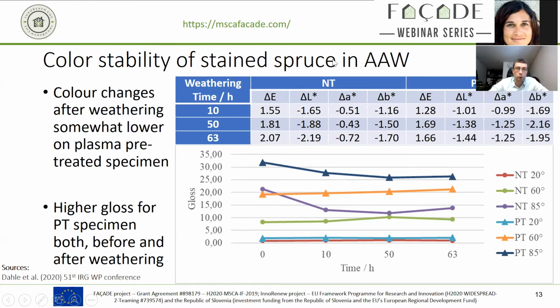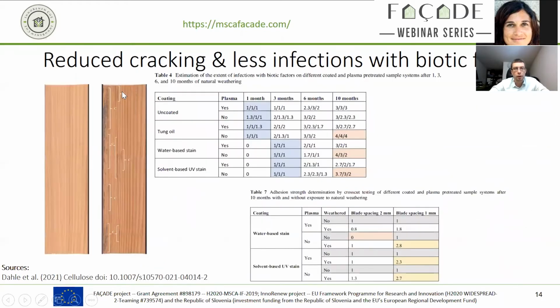Color stability can be improved, but this is not the case for all materials. In the case of spruce, we found that color changes after weathering of a spruce sample that was plasma treated and then coated with the stain are less pronounced than for one that was not plasma treated before coating with the stain. But these effects are rather minor and are not the main benefits of the plasma treatment.